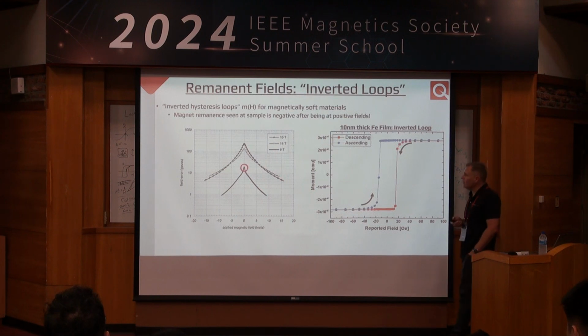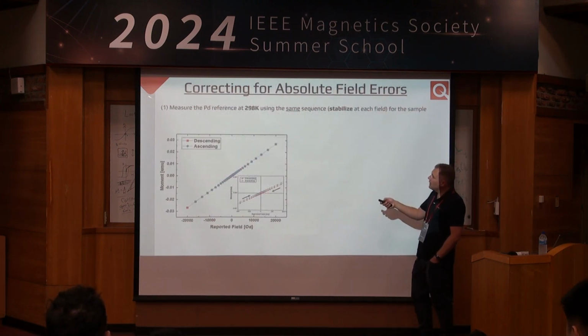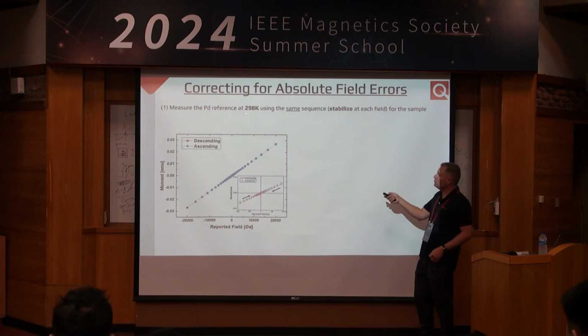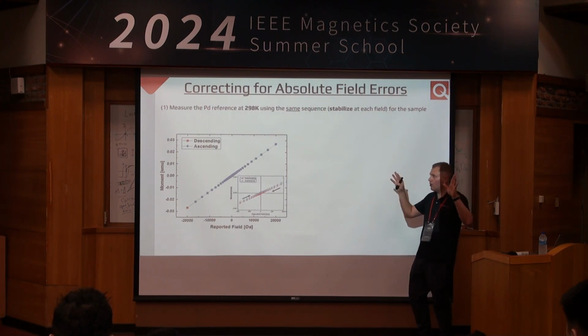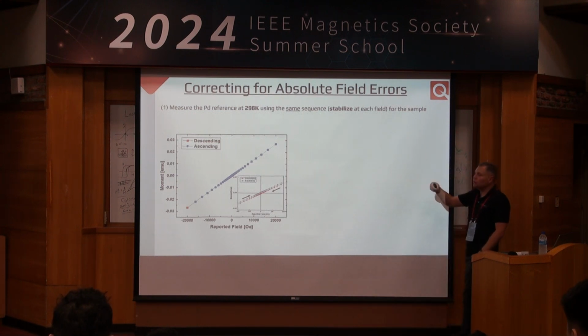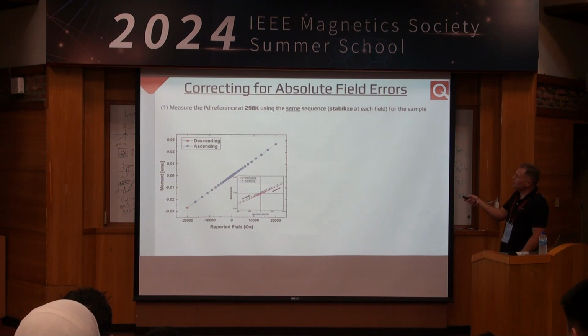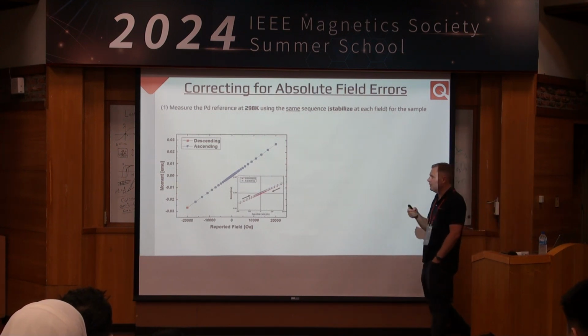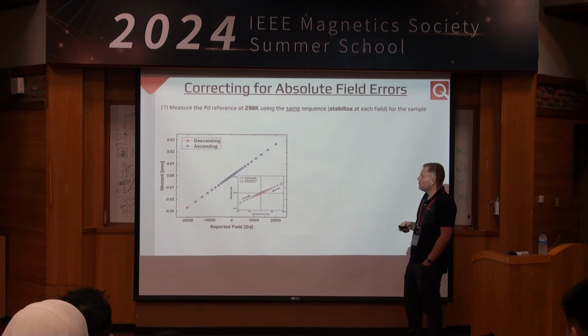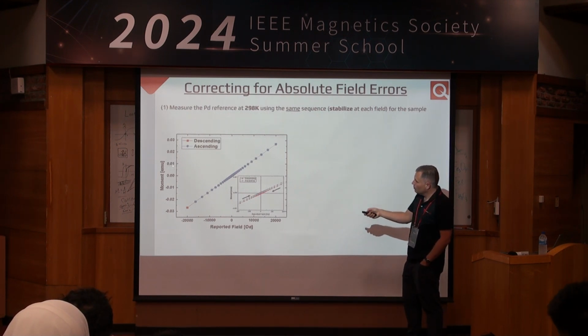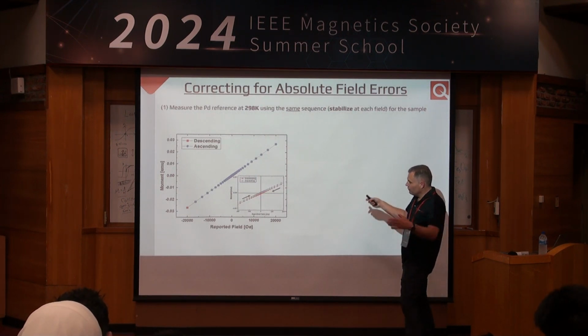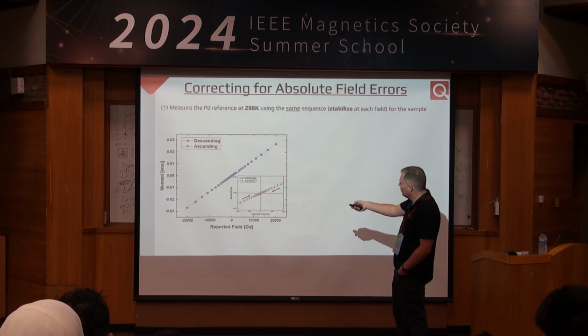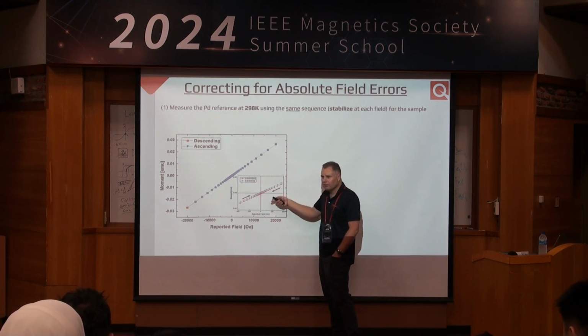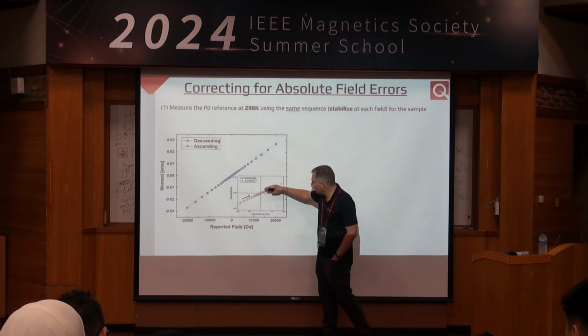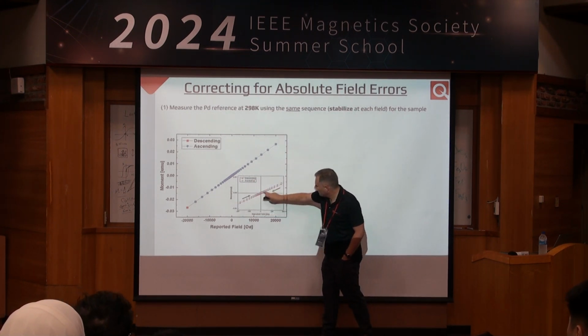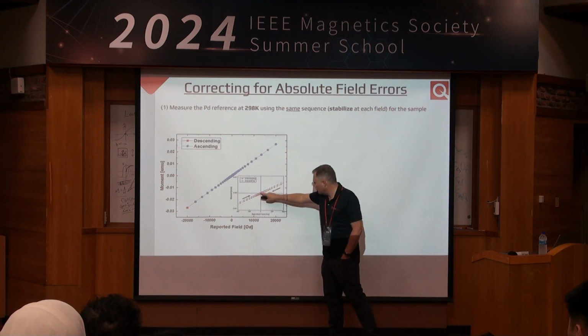So a very easy way we can solve this is simply to measure the palladium reference sample that we provide with all of these systems. You measure this palladium reference sample, which is an ideal paramagnetic sample, using the same sequence that you'll use for your sample, except for the temperature. And we want to measure at 298 Kelvin because we know the susceptibility of the palladium reference sample very well at this temperature. So that's shown here. So, moment versus field, ascending and descending branches. From way out here, it looks okay. It's a straight line. It's a paramagnet. But zooming in, we see hysteresis here. That's not real. That's instrument artifact. And we see the same sort of inverted loop where the descending branch crosses here, the ascending branch crosses here. But we know it should go right through the origin, both of them.